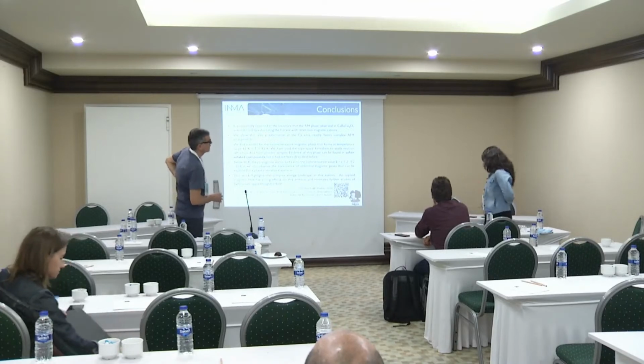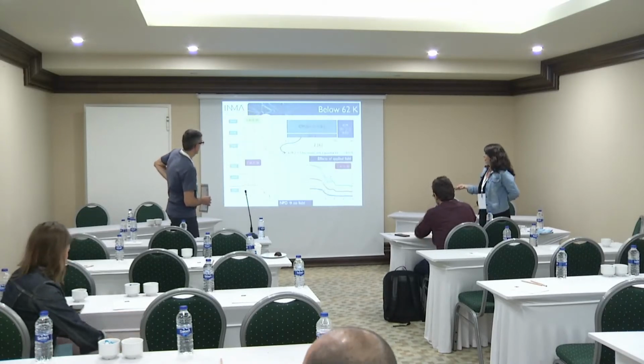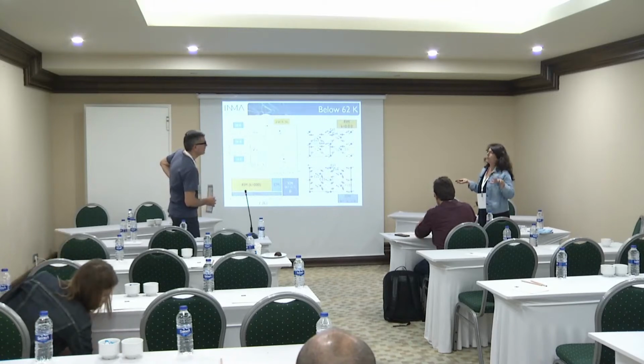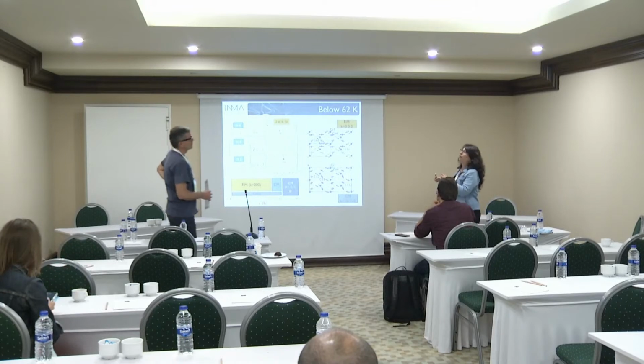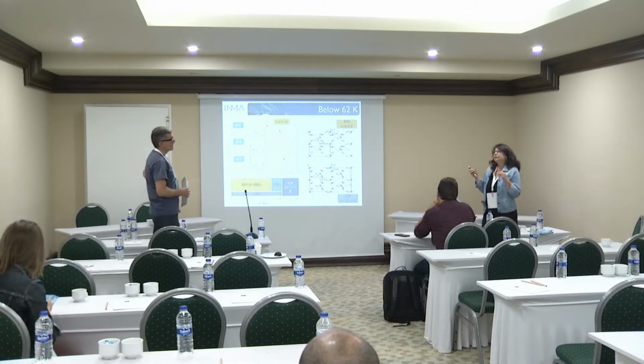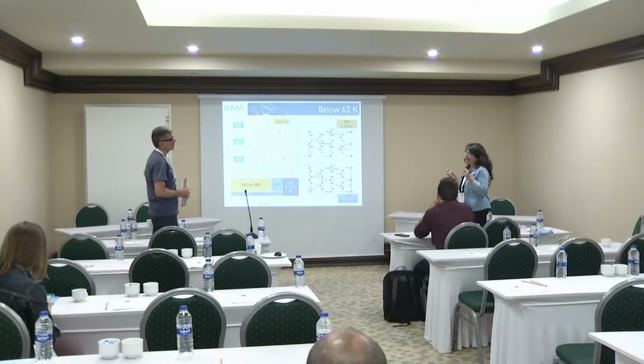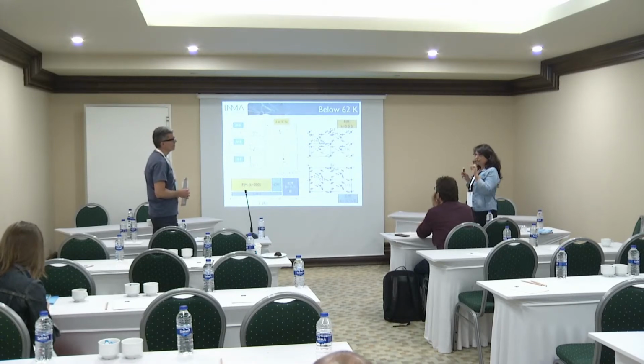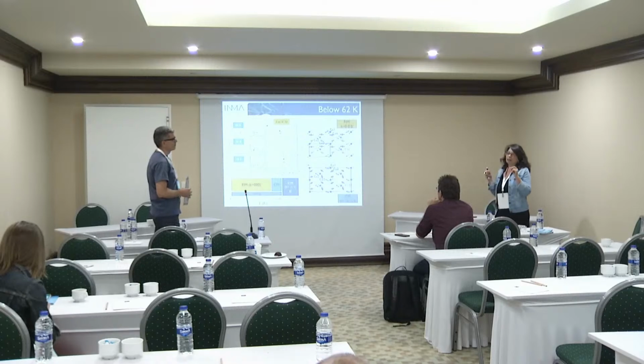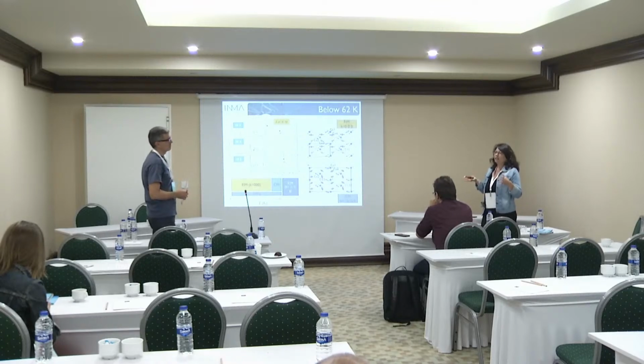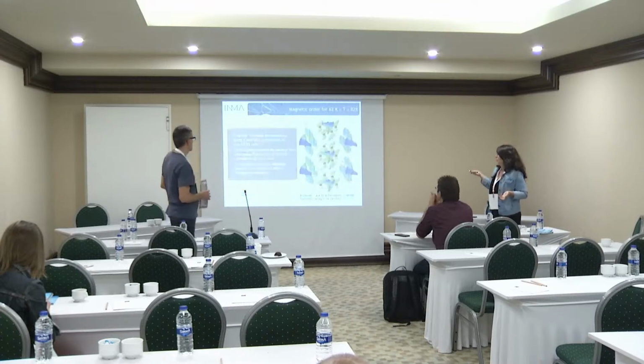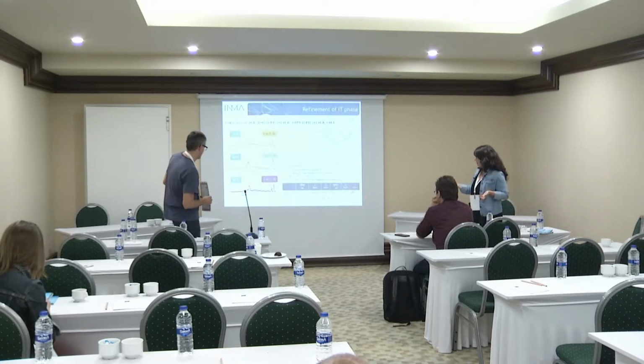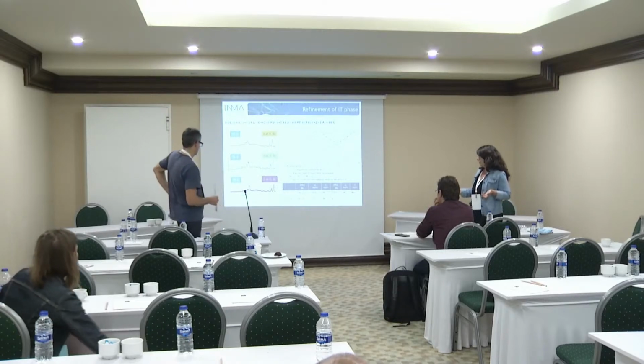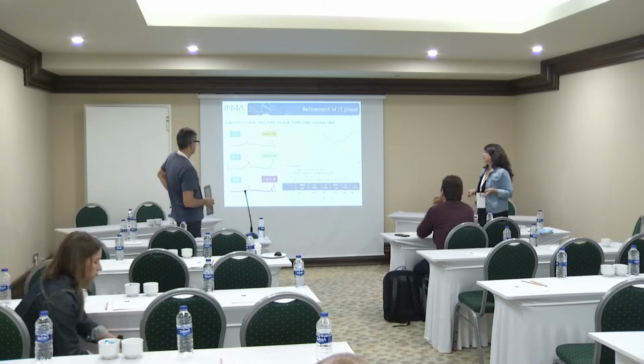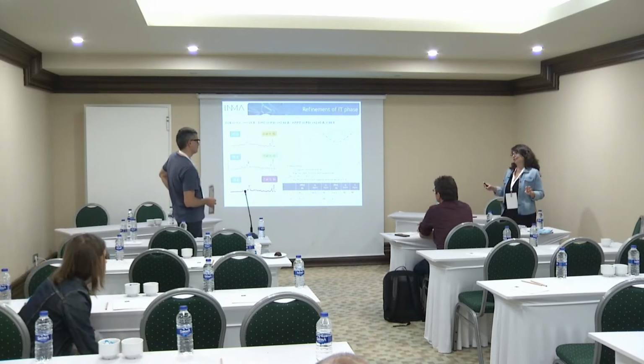You have slightly different models. I think I went very quickly over that. But charge order was proposed in the first publication of this structure, but it was based only on a difference of interatomic distances, and it was not very robust. Some years later, people conducted more precise synchrotron radiation measurements, and they showed that you really can't justify a charge ordering scenario. You can see that there is a difference between the strength of the magnetic moments, but you can't really say that it's charge order.